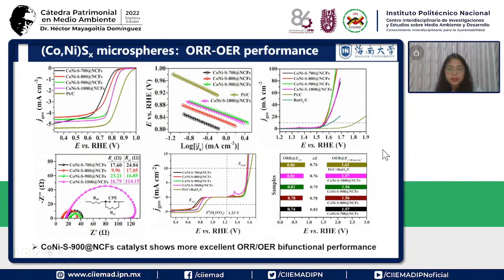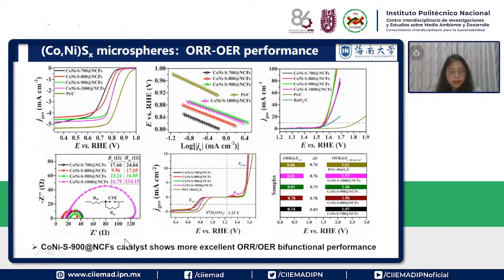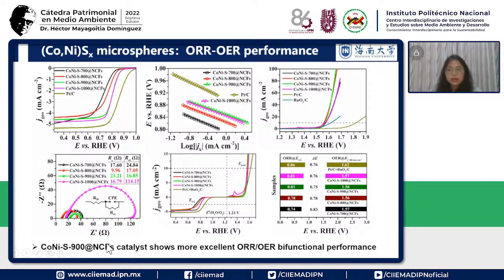And then we test their activity for the ORR and OER. Here we show the performance. After we compare the bifunctional performance, this sample, the 900 temperature catalyst, shows a smaller value compared to the other temperatures and the commercial platinum and ruthenium oxide. The value is 0.75, a little bit lower than the others. So we can say this material shows more excellent ORR and OER bifunctional performance.